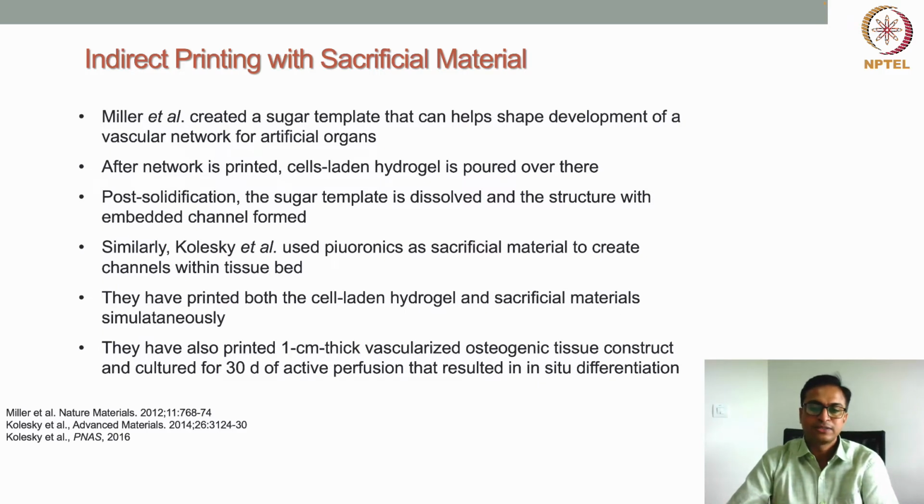And then they lowered the temperature to less than 20 degrees centigrade, where the Pluronics is liquefied, and then the Pluronics can be taken out easily by suctioning. So in this work they have shown that by using Pluronics as a sacrificial material, a cell-laden hydrogel with embedded channels can be created, and these channels can be further endothelialized by perfusing endothelial cells in media through the channel. So the endothelial cells go and bind to the innermost layer, the inner lining of the channel,